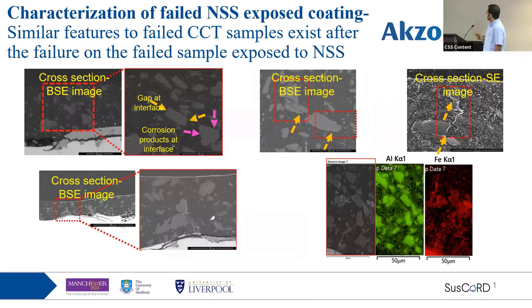So now I move on and characterize the coatings that were exposed to the neutral salt spray test. Specifically, these are all the samples which actually showed failure, because the other samples didn't show any failure. So what happens is, after the corrosion initiates and the blister forms, what we saw is completely similar to what we observed for the samples exposed to the cyclic corrosion test: corrosion product depositing at the interface of the particles, cracks within the coatings, also the interface of aluminum hydroxide particles getting filled with corrosion products, and so on.